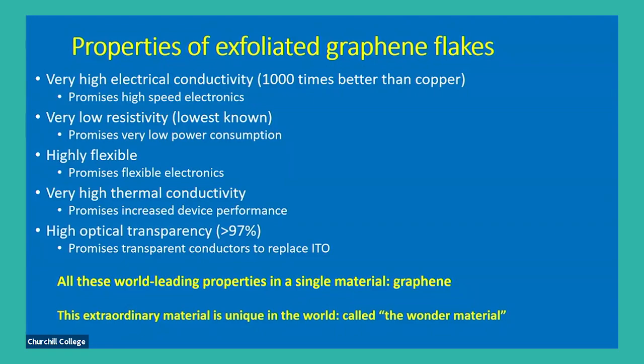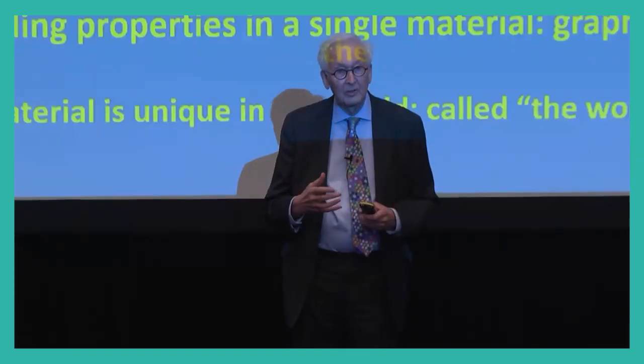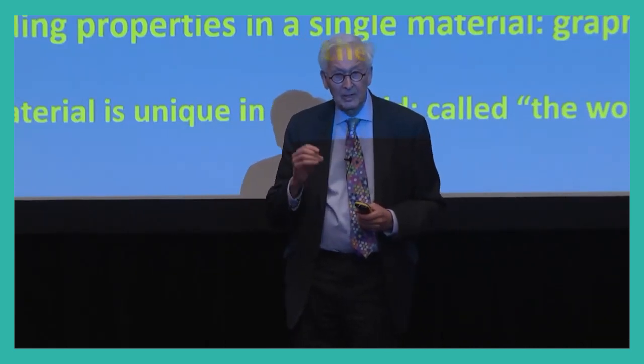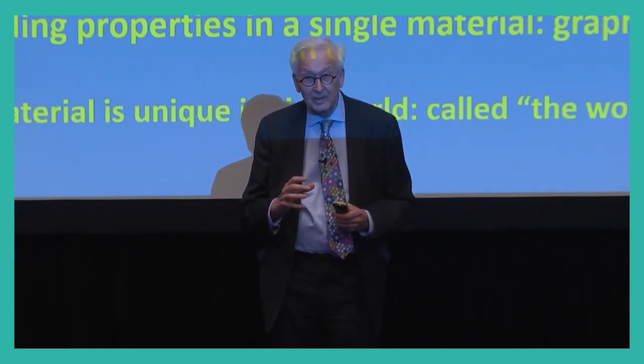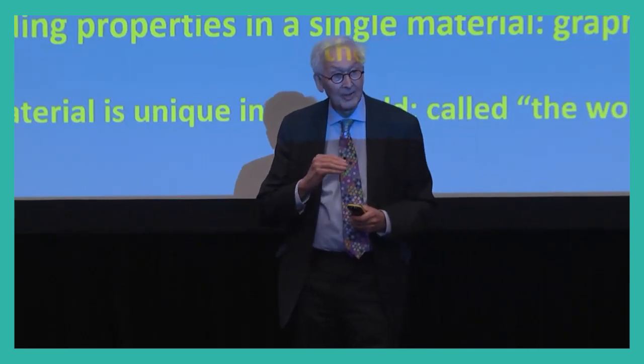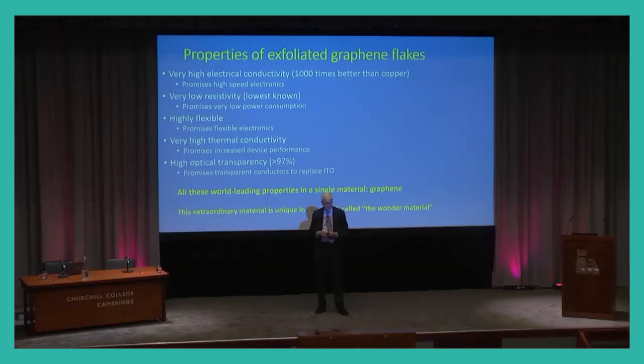In fact, as Athene said, when I was in Cambridge and before I worked on graphene, I was working on gallium nitride devices, to start with LEDs and then electronic devices. And the power you can use for gallium nitride electronic devices or other high power devices is limited by the heat they generate, which you've got to get rid of. So gallium nitride electronic devices like transistors only operate at about 1/3 of their capacity because you just can't get rid of the heat if you operate them at higher current densities. So if you have graphene devices, because it's such a good thermal conductor, that promises good device performance.